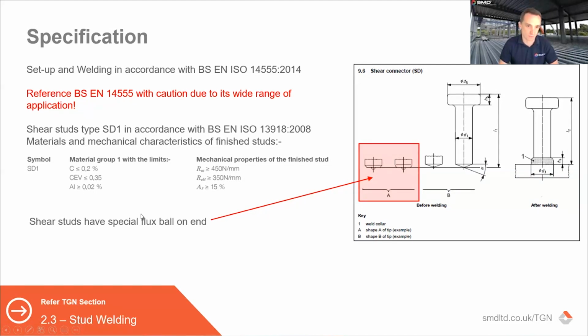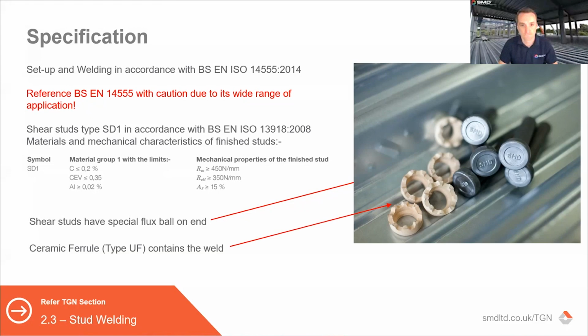Bit of material information there. The key thing is that the ultimate tensile strength of the shear studs is 450 for the purpose that we're using them and that we require for composite beam design. And the ferrules that are used with those shear studs to weld the stud to the beam, whether that be through deck or direct to beam, is a type UF. Again, that is detailed in the standard, but you can see one in the image on the right there.